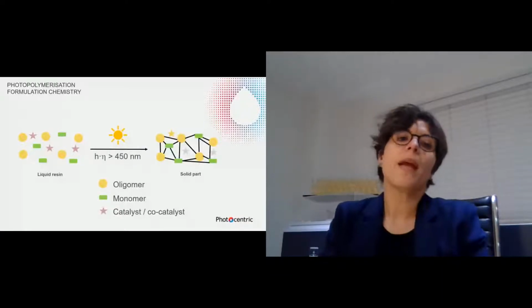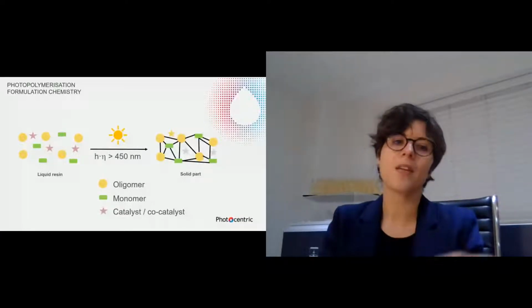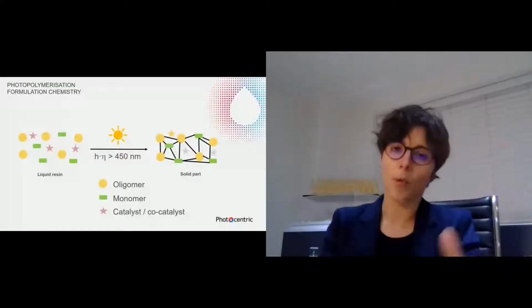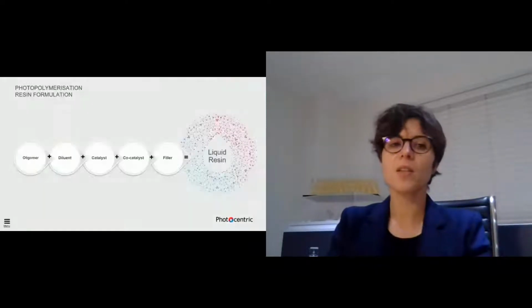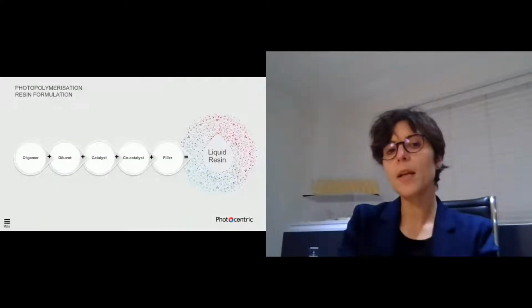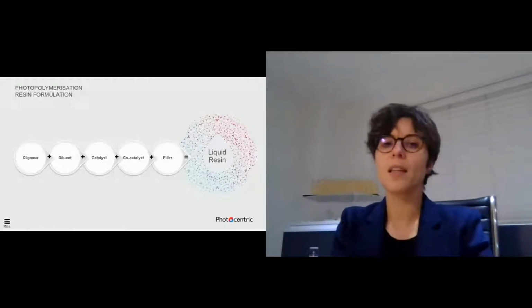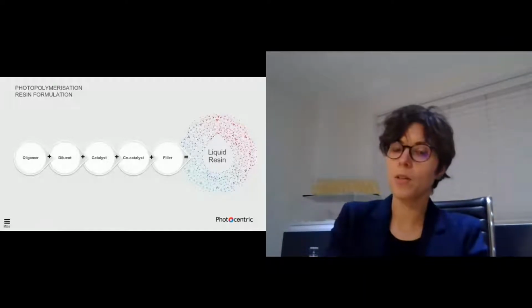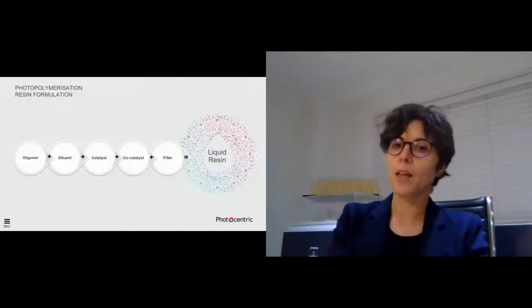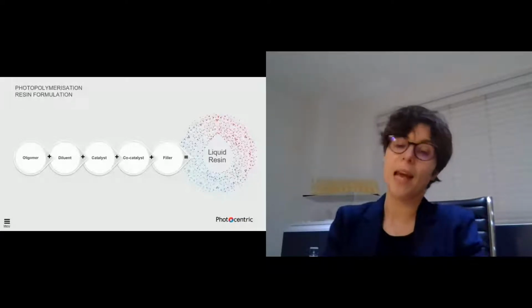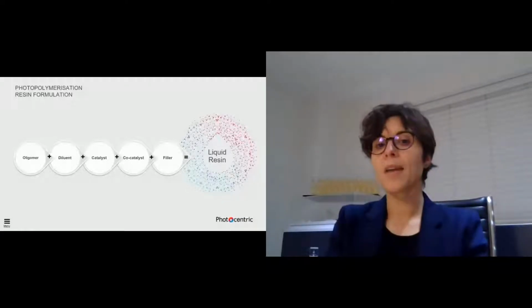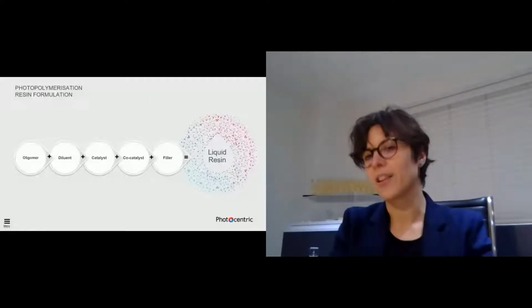And whenever you create your resin formulation, as I said, you have oligomers, which dictate the mechanical properties, but they're usually very viscous, so you use a variety of monomers as diluents. You have a catalyst and co-catalyst, and a variety of filler materials. So you can have either ceramic or metal particles to enhance thermal or mechanical properties, or you could have a variety of pigments to give you a nicely colored resin.